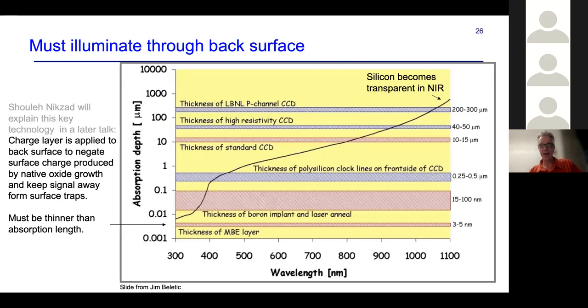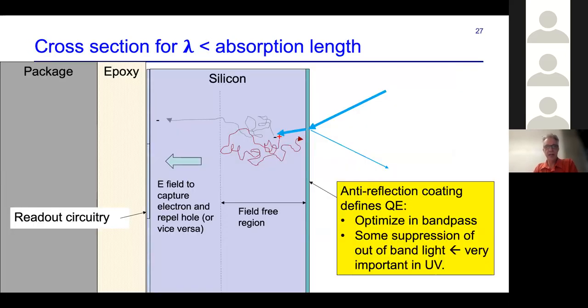This diagram just illustrates the relative thickness of various layers in silicon sensors with a focus on CCDs. And what you can see here is that when we're down at the ultraviolet end of the curve on the left, the absorption length is in fact shorter than the thickness of any of the electrode structures which we might put on the front surface. And this means that we absolutely have to illuminate the sensor through the backside so that we don't lose our electrons in the electronics. So this view here shows you the silicon from edge on.